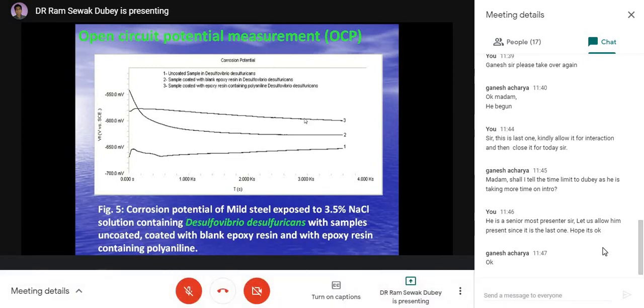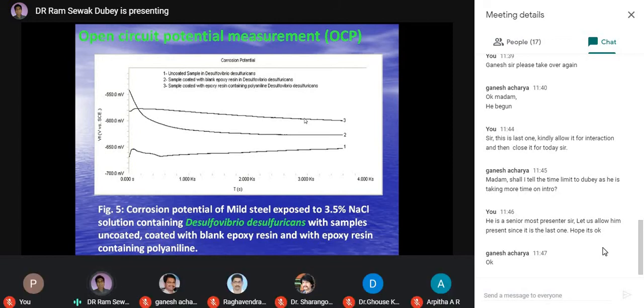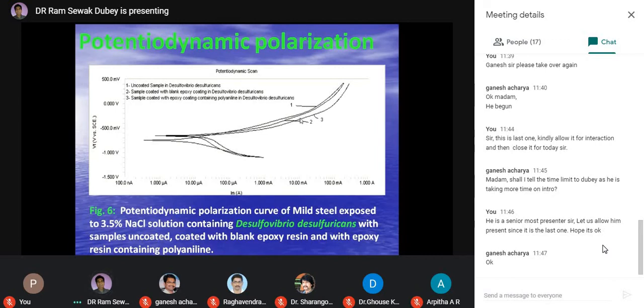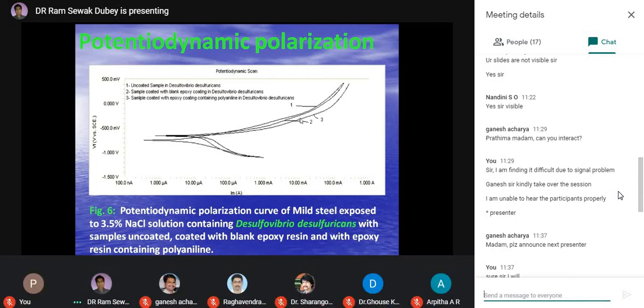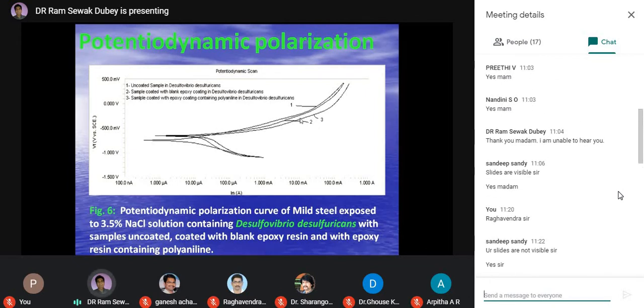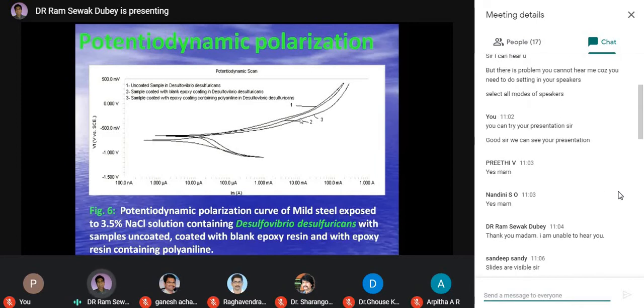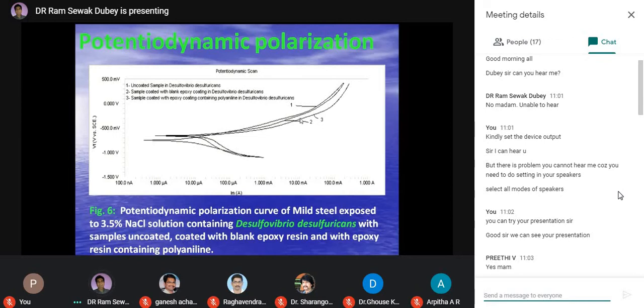After performing the open circuit potential experiment, which took a few hours to several days, anodic polarization was performed. We call it a potentiodynamic scan, without application of any particular inhibitor, with simple coating and coating impregnated with polyaniline in the medium. Number 1, the uncoated sample, had a very high corrosion rate. And number 3, the coating containing polyaniline, had a quite reduced corrosion rate, which indicates that at this particular potential, it is unable to make it so anodic that it results in loss of the material, loss of the iron.